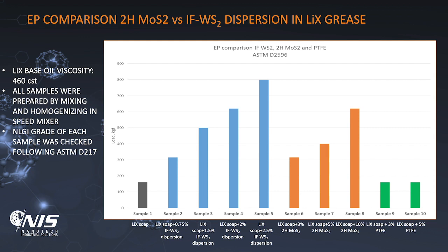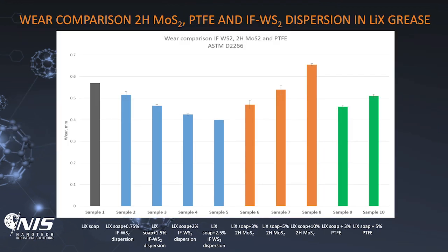I have several slides on greases as well here, and it's a comparison of grease with IFWS2, with molybdenum disulfide, and with PTFE. So we see that with IFWS2, we got an increase of the weld load from 160, which is regular lithium complex grease, to 800 kilogram force. With molybdenum disulfide, going from 3 to 10%, we got an increase in EP. However, it was not as good as with a much lower concentration of IFWS2. But with PTFE, with 3% and 5%, we didn't see any EP improvement. So it stayed at the same level. However, it improved some anti-wear properties.